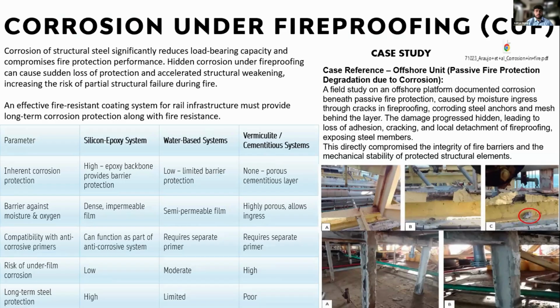A field study on an offshore unit documented corrosion beneath passive fire protection caused by moisture ingress through cracks in fireproofing, corroding steel anchors and mesh behind the layers. The damage progressed hidden, leading to loss of adhesion, cracking, and local detachment of fireproofing, exposing steel members. This directly compromises the integrity of fire barriers and the mechanical stability of the protective structural elements. Here I've made a comparison as well.